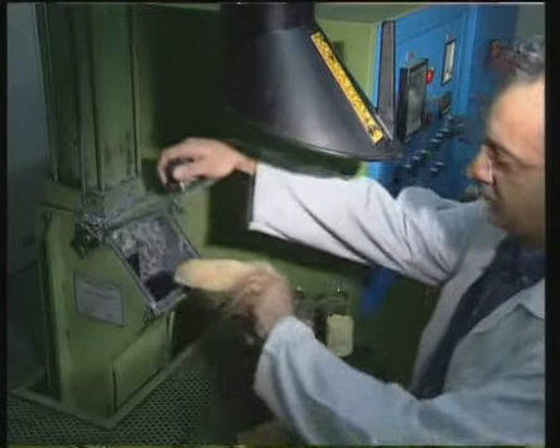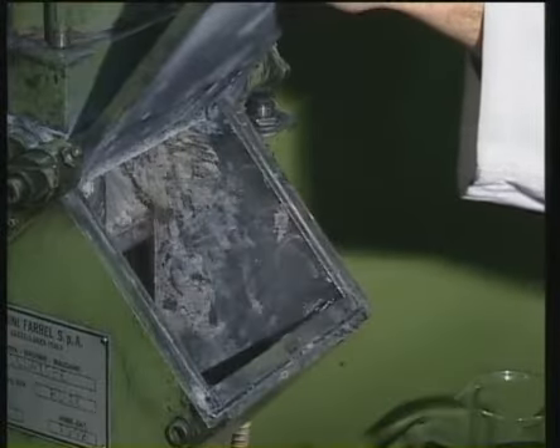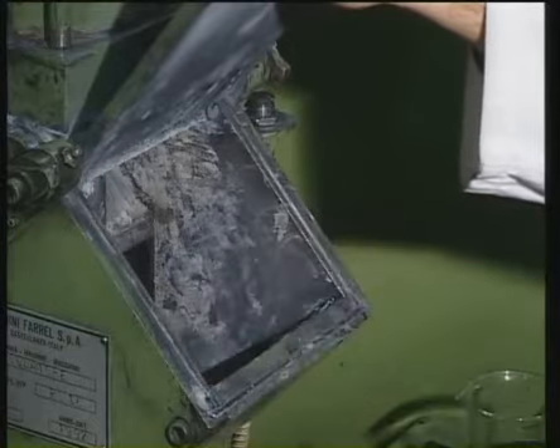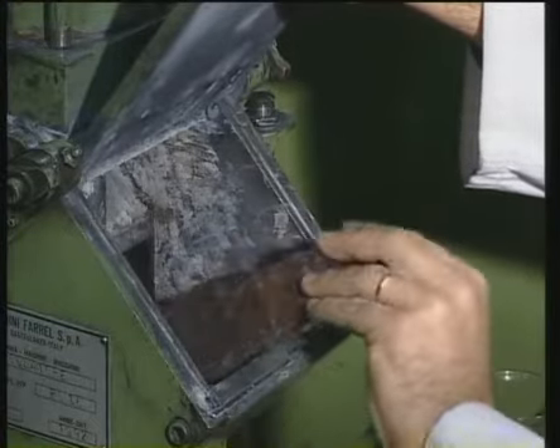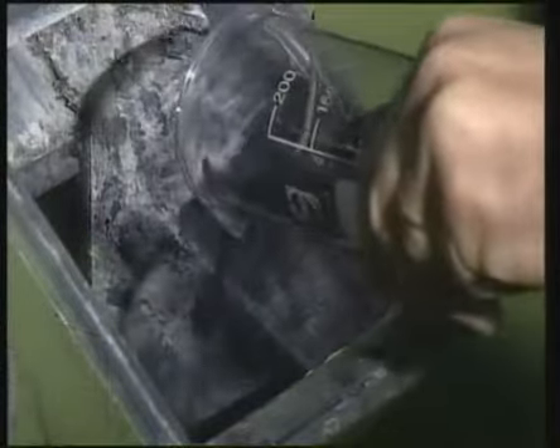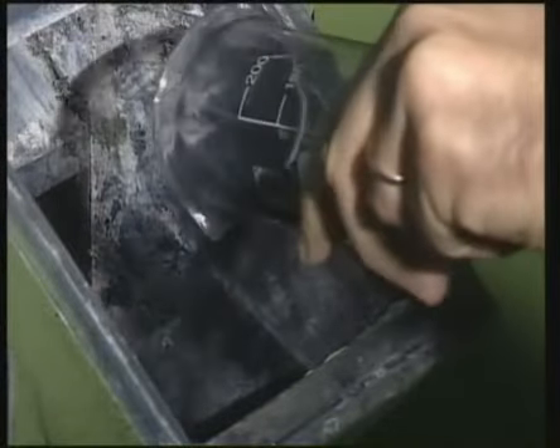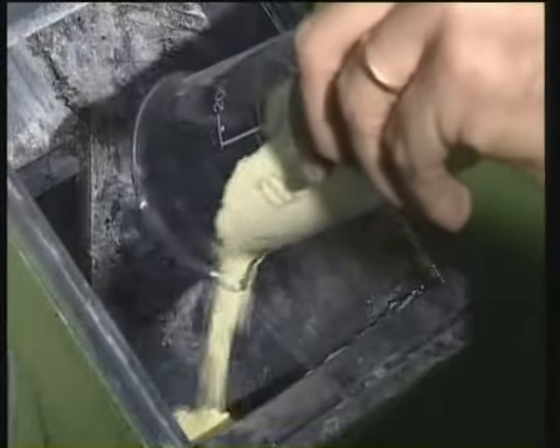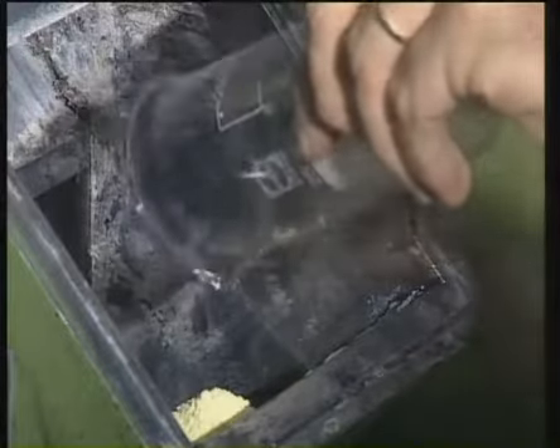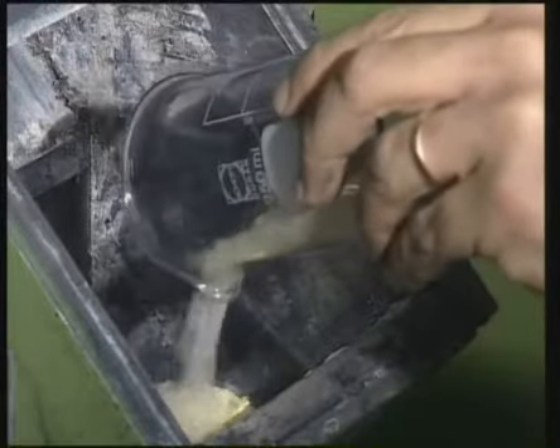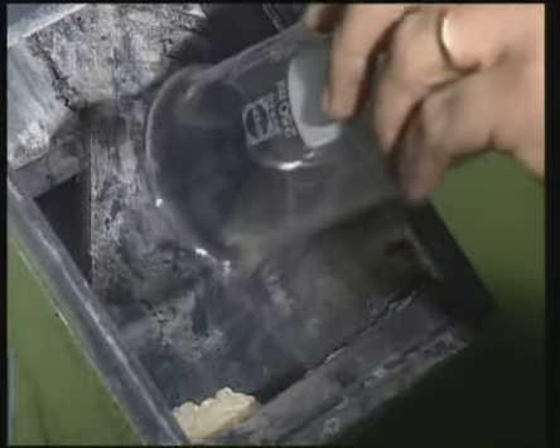Now we'll see the ingredients being placed in the Banbury mixer in the chemical laboratory. For better detail and picture quality, this is the same as those used in the compounds department, but much smaller, with a capacity of just 2 kilos. The three Banbury mixers in the Anagni factory, on the other hand, have a capacity that is 100 times greater and take less than 4 minutes to prepare 200 kilos of compound.